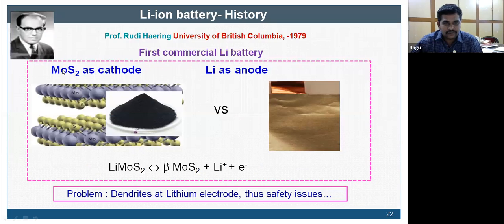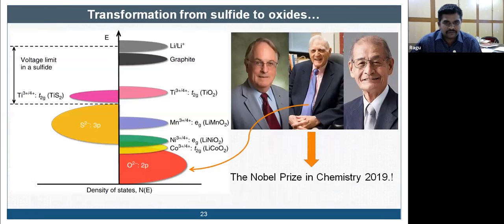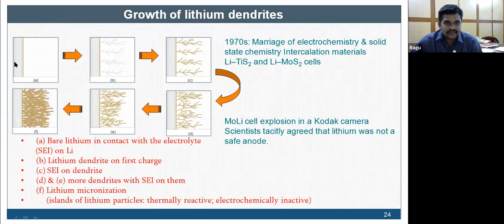He was the first guy who has taken this metal sulfide and coupled it with metallic lithium. And he could succeed in delivering a potential like 2.2 volt. So during charge-discharge cycling, he found that there was a dendrite growth at the surface of the metallic lithium. Okay, so what is dendrite? Dendrite is a growth of a needle-like kind of film. Look at this. This is called the dendrite growth.